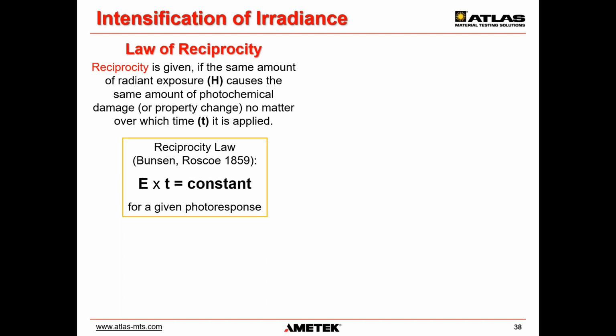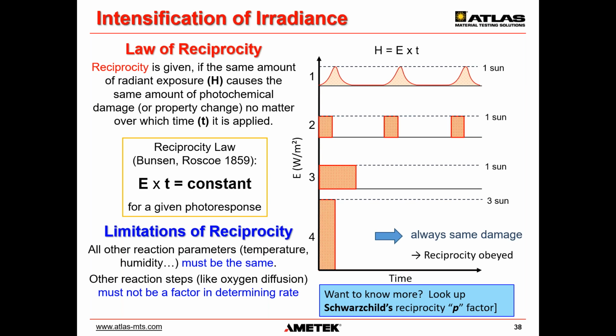This principle of reciprocity refers to running a test with higher irradiance than normal conditions for a shorter time, but to the same radiant exposure of a natural exposure at normal irradiance for a longer period of time, and asking, are the results the same? To put it simply, can I get the same result in half the time by exposing my material to twice the irradiance, or in a third of the time with 3 times the irradiance, etc.? Or in even simpler words, do 2 photons of the same energy do exactly twice the damage of 1 photon?